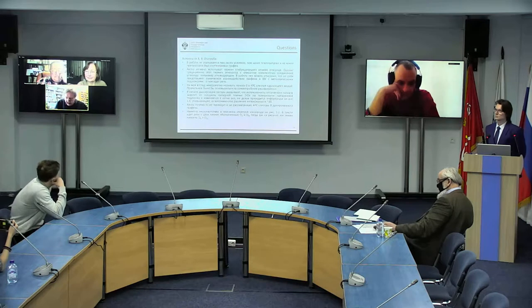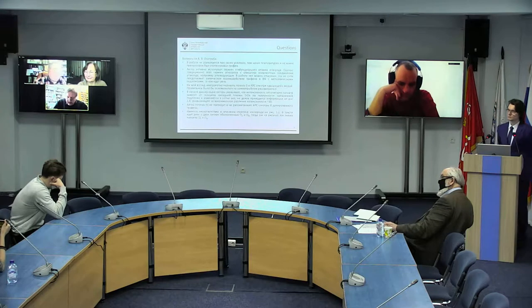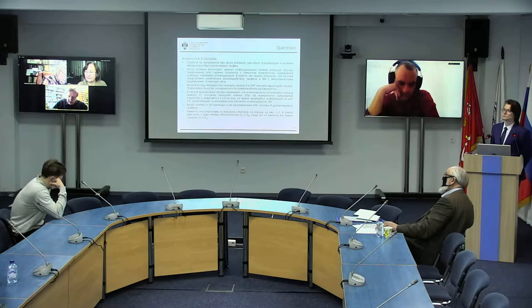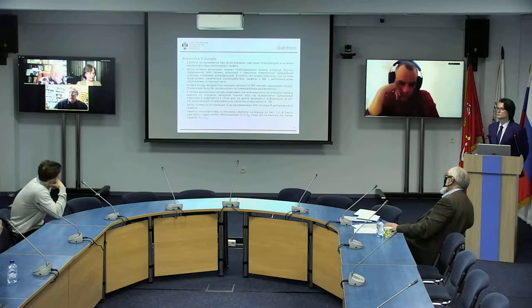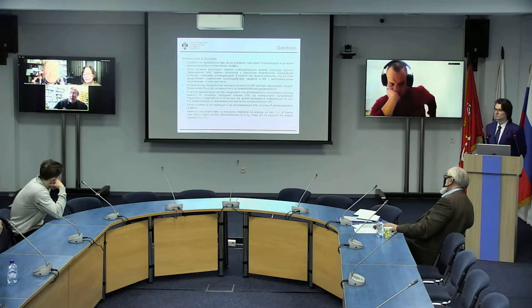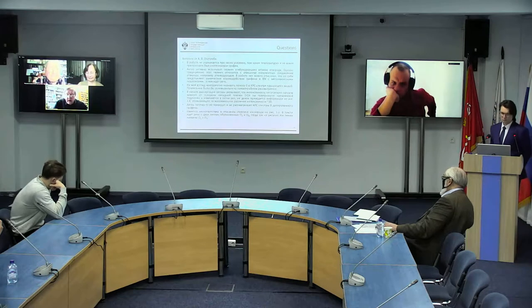Third point, I believe it's not correct to call this G band in a Raman spectrum a breathing mode. And at the start of the thesis, you mentioned that the intensity of the optical signal depends on the thickness of the oxide film. And then you see that there are hundreds-of-times changes, and finally give diagram 1.6 where you mention that the maximum difference is 30 in this intensity due to interference.